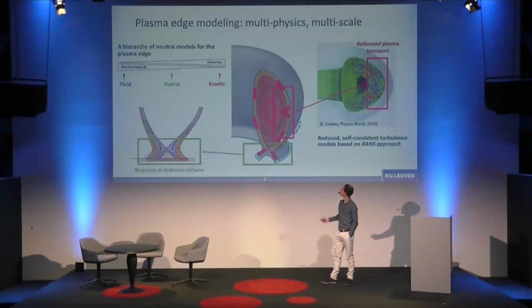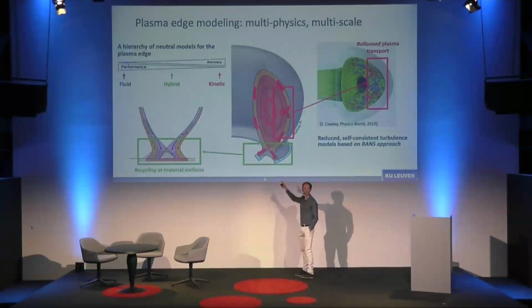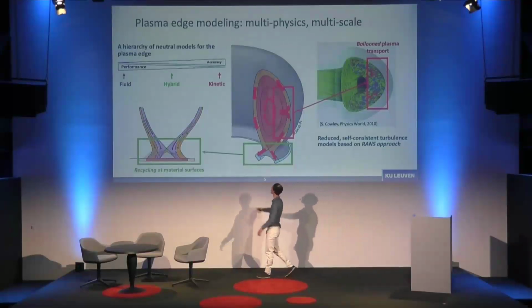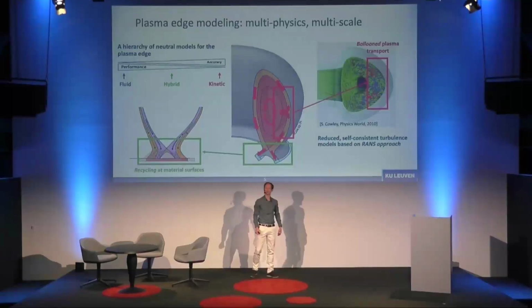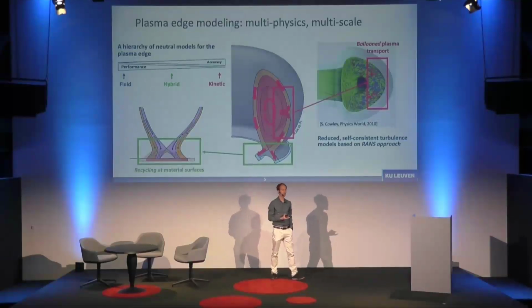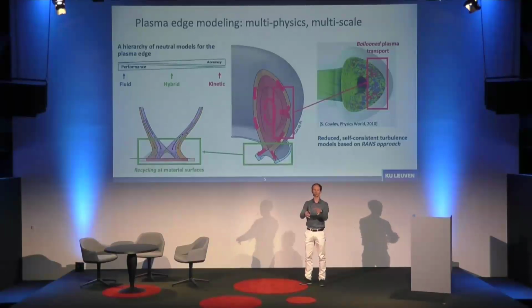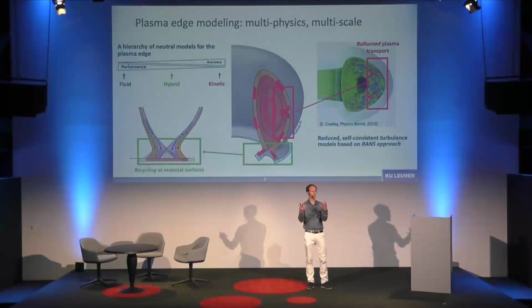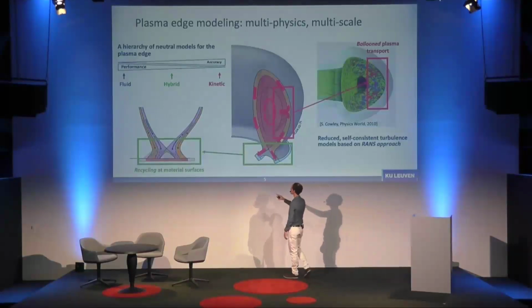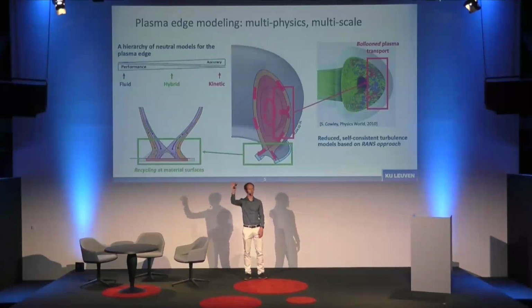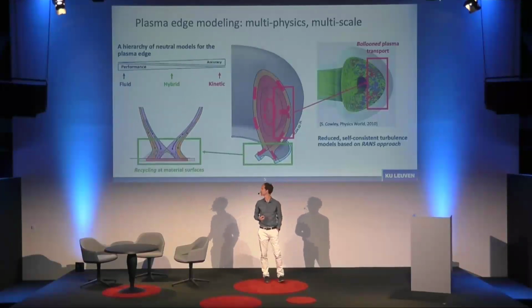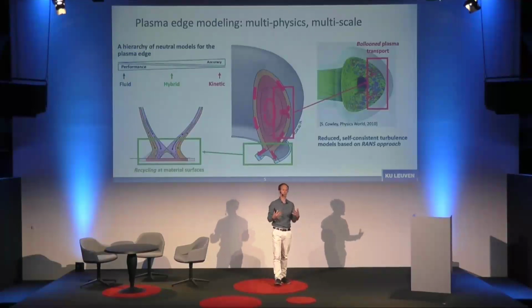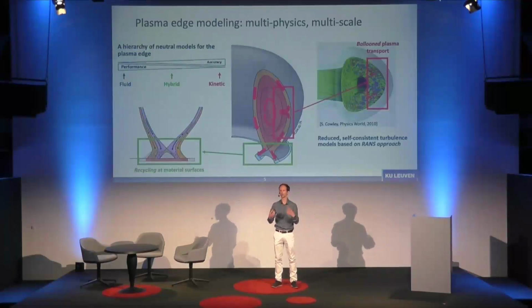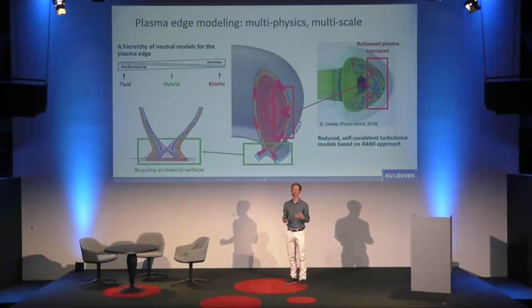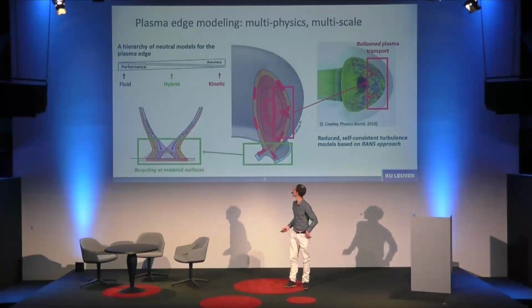Then the next step of the modeling that we focus on is what actually happens there in the divertor. At some point you have your plasma coming down from the core towards the divertor. These are charged particles, ions and electrons. At some point they hit the wall, they neutralize, so they recombine, they become neutrals, atoms and molecules, and then they recycle back into the plasma. Now these neutral particles, as we've seen, are not bound by the magnetic field, so they scatter all over and start colliding with your plasma. This is actually a very wanted effect because by these collisions you can dissipate a lot of energy before the plasma actually reaches the surface, and in this way you can protect your material surfaces by so-called high recycling or detached conditions.